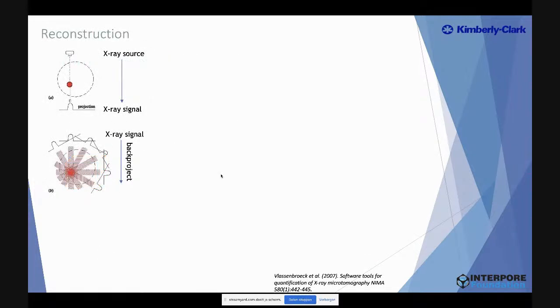So after having a stack of radiographs, we need to go to the 2D and 3D images. And we do this by reconstructing the signal. So on the left, you have a scheme showing what is really happening: you have an X-ray source and an X-ray signal that is printed on your detector, and here you have your sample. This X-ray signal is taken here at one location, but in reality, while rotating our sample, we have this at each location, and then you back project the information of your X-ray signal, and this allows you to reconstruct your original object in a non-destructive way.